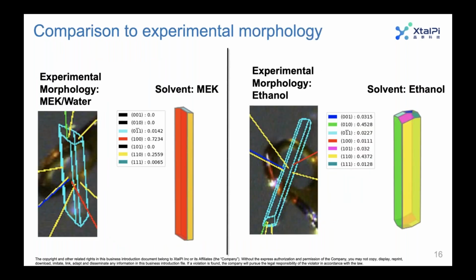However, the experimental results obtained up to this point had yielded needle morphologies. So there was this flat needle obtained in a mixture of MEK and water, and also this needle obtained in ethanol. So the first thing to do was to verify whether or not the simulations could predict these results. So in pure MEK, we get something that's very similar to what was obtained in MEK and water. And we could do a binary solvent system. That just wasn't what was asked at the time. And in pure ethanol, we obtained something very needle-like and very similar to what's obtained experimentally.